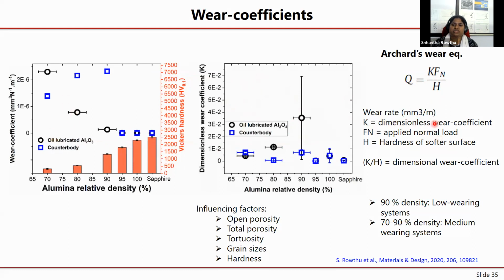So one could plot both the dimensionless as well as dimensional wear coefficient, and we can see that especially if you look at this wear coefficient, for the higher dense specimens, the wear coefficients are very small, almost like 10 power of -8. In the last 2-3 cases or so, I could not detect any mass changes at all. So that means these are very, this is wrong. It's not 90%. It is greater than 90%, guys. Let me correct this one here. So these are very low wearing systems. But in the case of 70 to 90%, that is these 3 cases, it's a medium wearing system. Of course, the 90% seems to be having again a small value around 10 power of -7 millimeter cube per Newton per meter. So not only in friction coefficient, but in terms of wear coefficients also, it is doing fairly well. Okay.